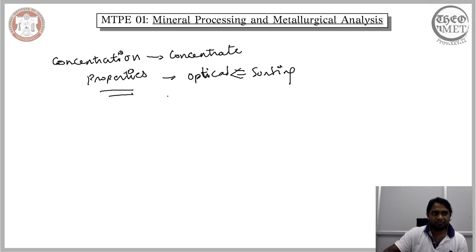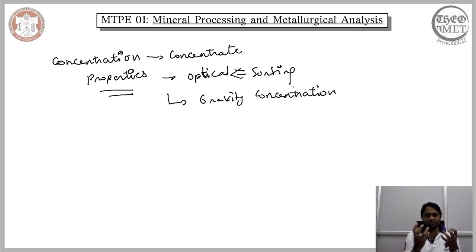The other technique involves gravity separation or gravity concentration. The overall process of gravity concentration involves this mixture of fragments, comprising concentrates, middlings and tailings, being suspended in a given fluid or medium and allowed to move. Depending on the movement of these individual particles, they are separated into concentrates and the rest. So again, what is essentially being done is a definite degree of motion is introduced into this mixture of particles, and depending on the movements they exhibit, the concentrate is separated from the rest. The property that governs the movement of the individual particle is the density.